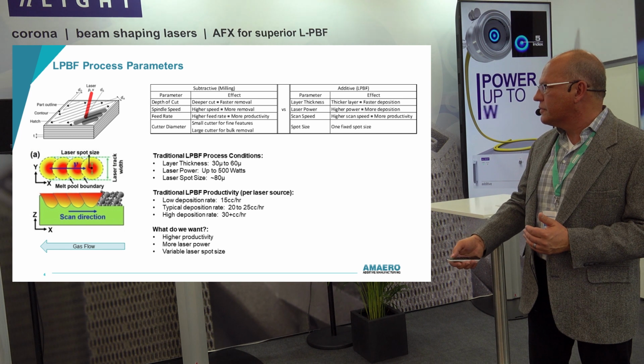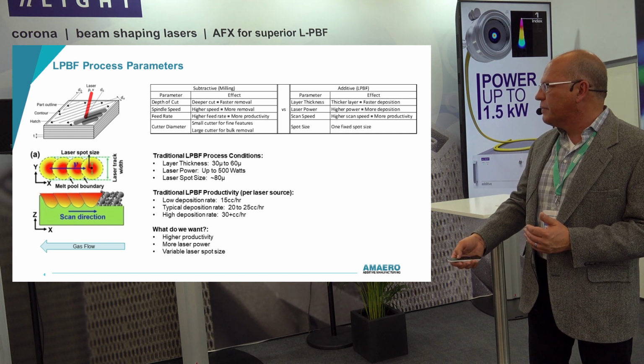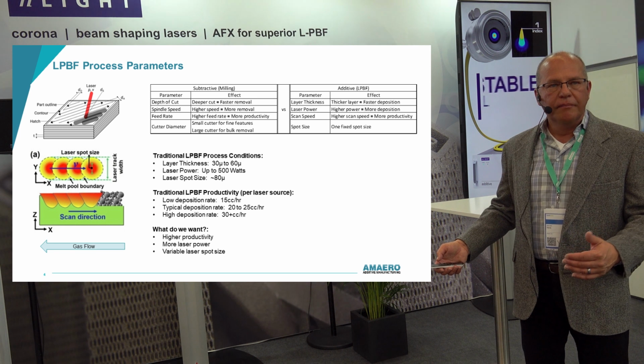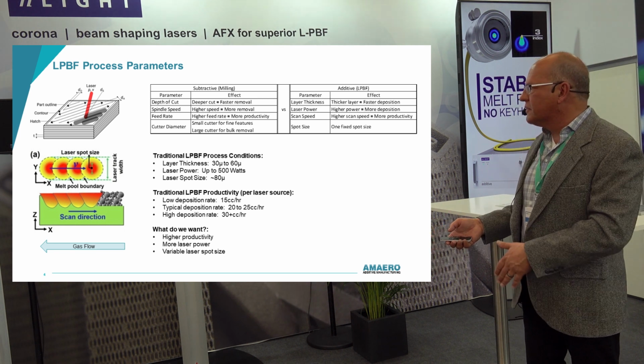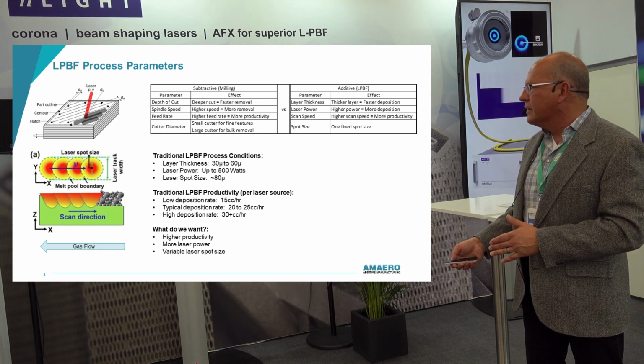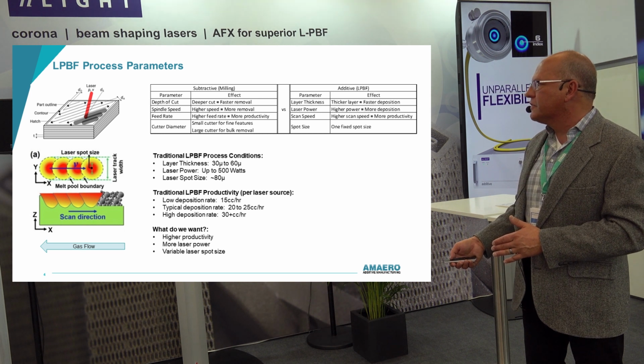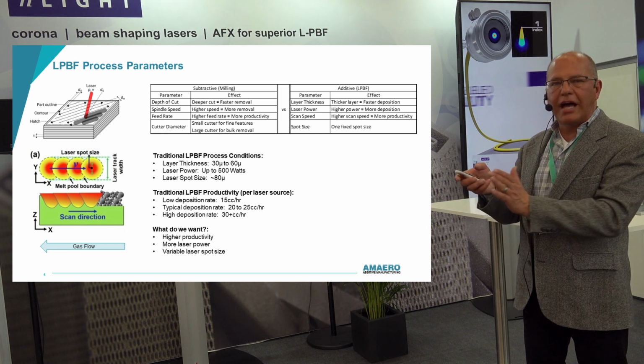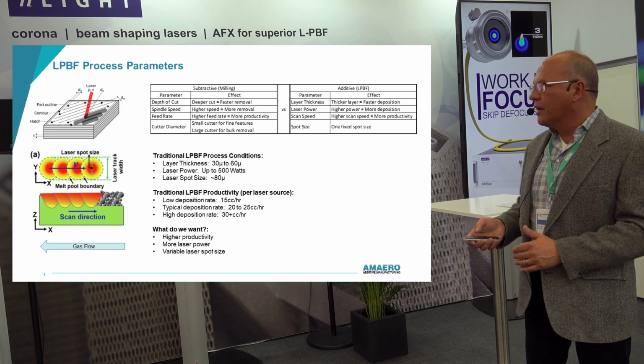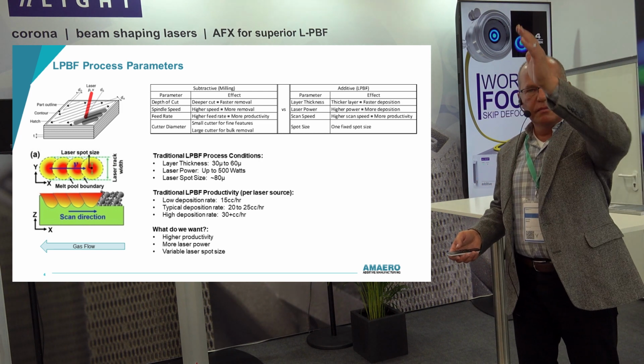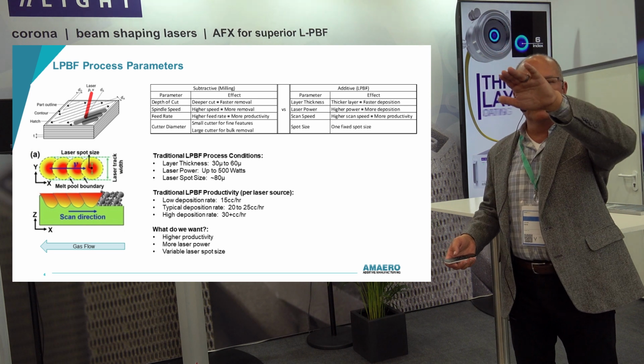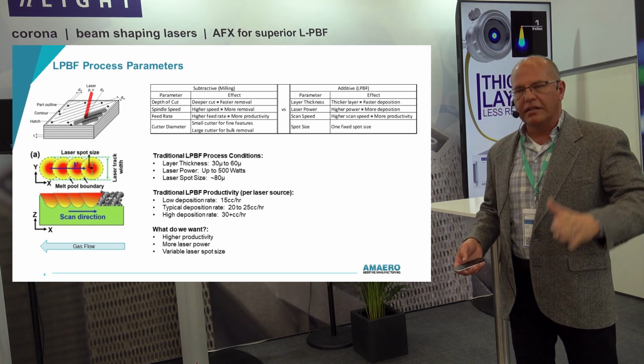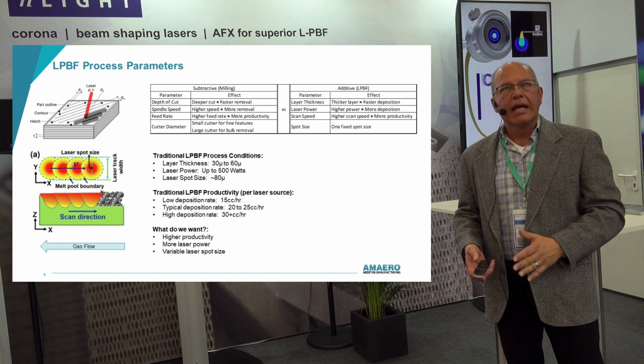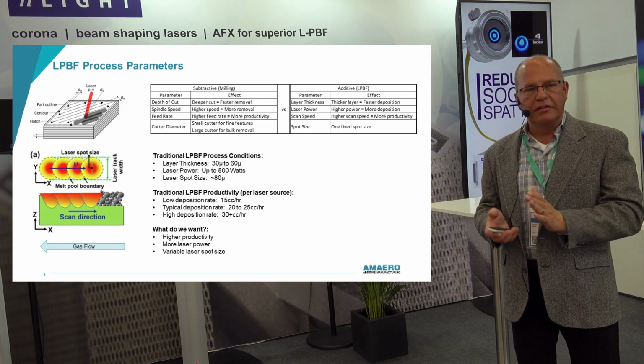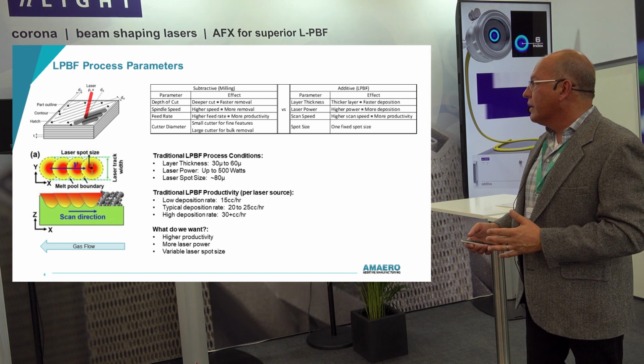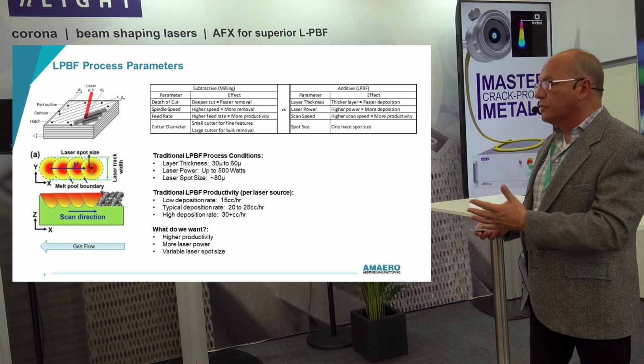And we have, as we can see, the Gaussian spot, which is hot in the middle and cold on the outsides, gives us this really deep melt pool, kind of like an inverted bell shape. As a result of that shape, we have to overlap our traces a lot. We follow this tool path, scanning up, coming over a little bit, overlapping, scanning down, scanning up, scanning down, constantly overlapping. The need to overlap a lot is also cutting into our efficiency. We have some other problems that we'll talk about in a moment.